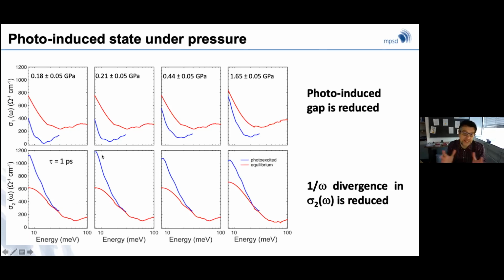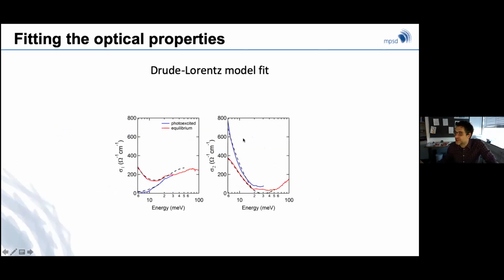So now I can use this effect. If I fit this data as a function of pressure and temperature, I can use these tuning parameters to try to create at least a proxy for a phase diagram for this non-equilibrium state. This is what Alicia did in great detail. She took these optical properties, as I did before when I was discussing the zero frequency conductivity in the context of the long-lived state. You take sigma 2, you check how divergent it is, and then applying the Drude-Lorentz fit, you can extract sigma 0, the real part of the conductivity, which should be infinity,